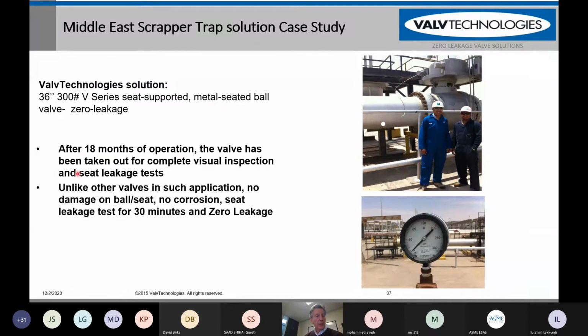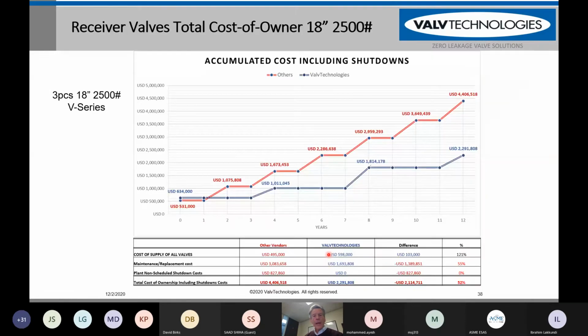This valve was put into service for 18 months of operation, as you can see right here, and then was taken out and was tested. It was held on test for 30 minutes. This is an actual picture of the gauge where it's being tested, and it has zero leakage. Why is zero leakage so important? Well, if you don't have zero leakage, then over a period of time, your valves will cost more and more and will give you less and less efficiency in your field.